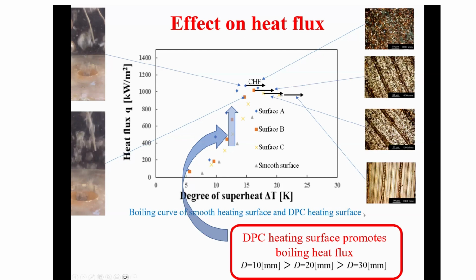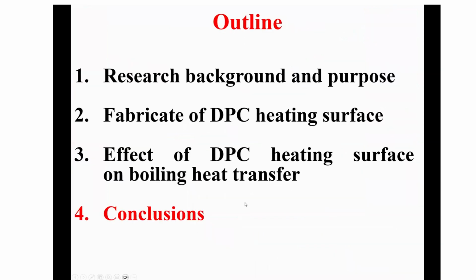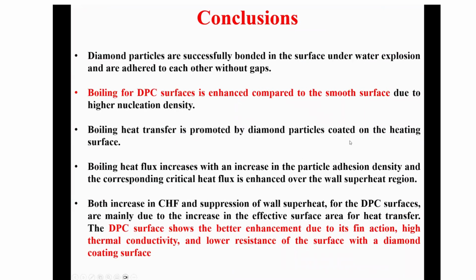Throughout the experimental results, I'd like to show the summary. Diamond particles were successfully bonded on the surface underwater explosion and adhered to each other without gap. Boiling on the DPC surface is enhanced compared with the smooth surface due to the higher nucleation density. And the boiling heat transfer is promoted by the diamond particles coated on the heating surface. Boiling heat flux increases with increasing particle adhesion density, and the corresponding critical heat flux is enhanced in the wall superheating region.